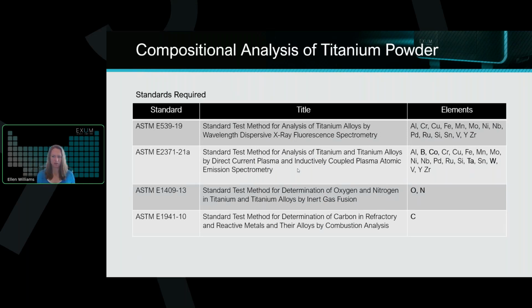But then neither of these techniques give you a sense of how much oxygen or nitrogen is in your powder, which would be important if we were doing recycled powder, or if we need to verify that our oxygen is not exceeding the specified limits for Ti-6-4. So then we're using that third test method and technique of inert gas fusion to get our oxygen and nitrogen, and then a fourth if your specific industry requirement needs you to verify carbon as well. So 4 different standards, 4 different analytical techniques in order to get all of the elements that you just saw on the previous slide, Massbox is capable of measuring.